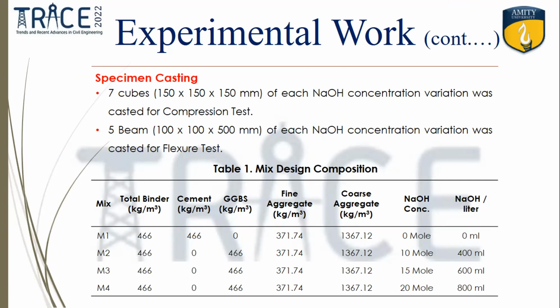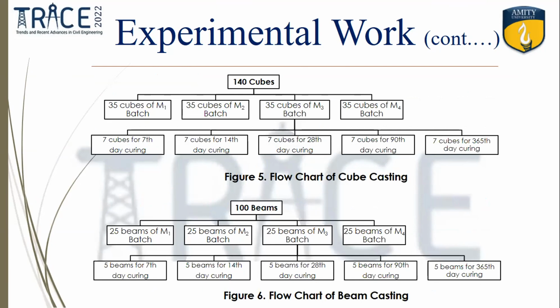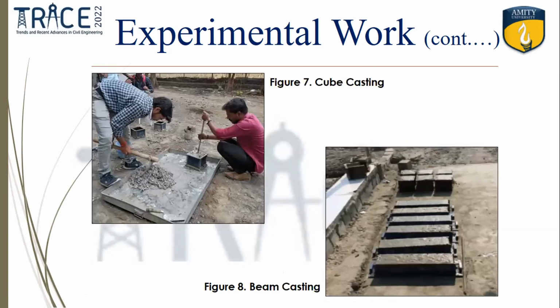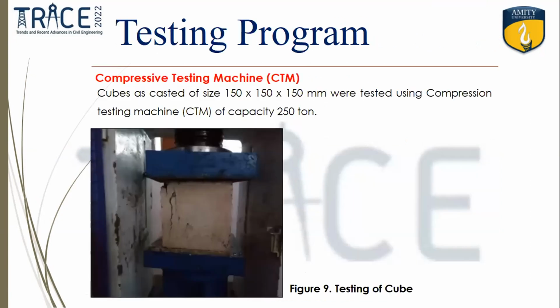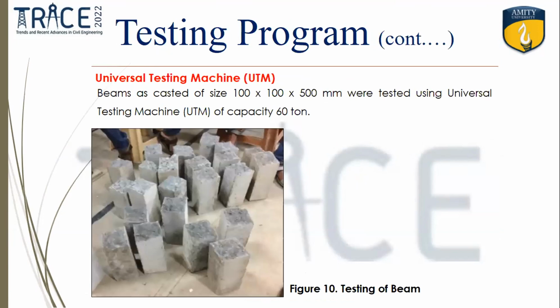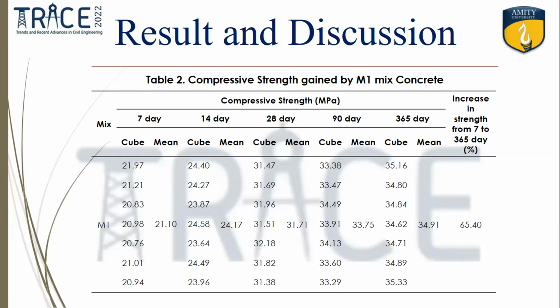And I also tested some beams for the flexural test. These were the flowcharts of cube casting. As you can see, 35 cubes of each mix were casted, 7 cubes for each day: 7th, 14th, 28th, 90th, and 365th day. Similarly, 25 beams of each mix were casted, 5 beams for each day: 7th, 14th, 28th, 90th, and 365th day. Cube casting was done, beam casting was done. For compressive strength, a CTM with a capacity of 250 tons was used. A UTM was used, which has a capacity of 60 tons. And these were my results.